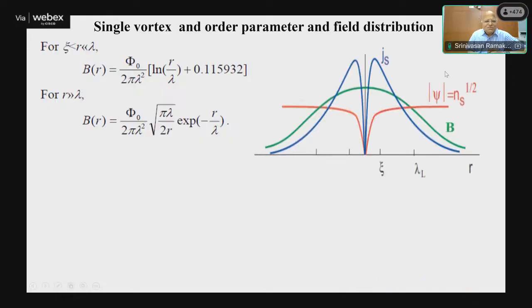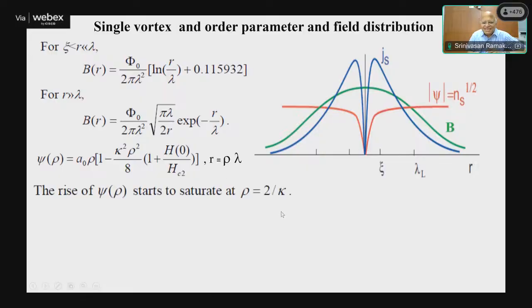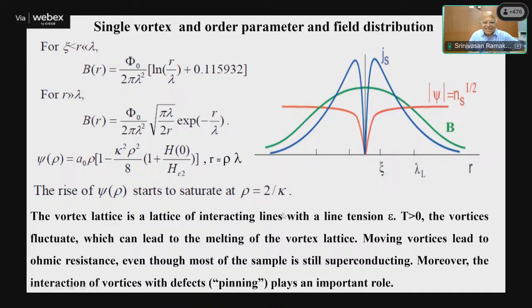We can also compute this. I am not going to do this computation. It depends on whether xi is less than lambda, that is the coherence length is less than lambda, or r is greater than lambda. So this is how the field penetrates. The superconducting fraction inside the vortex core goes to zero, whereas the field goes to maximum at this center. The superconducting current density also drops down in a single vortex.